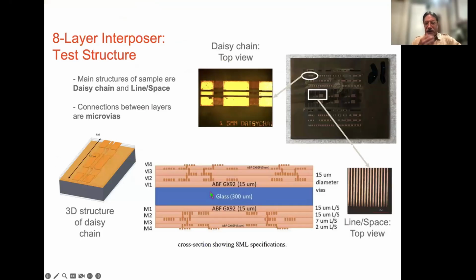So here is the test sample, a schematic cross-section. There's a glass core in this interposer, and then there are multiple layers of ABF film of different thicknesses, 15 microns and other thicknesses. And there's metallization at multiple levels. There are vias through the ABF film. There are basically two types of metallized structures in this test sample. There are daisy chains. These are metal patches that go up and down between two different levels. They're electrically connected. And there are line space structures. These are just closely spaced metal lines.